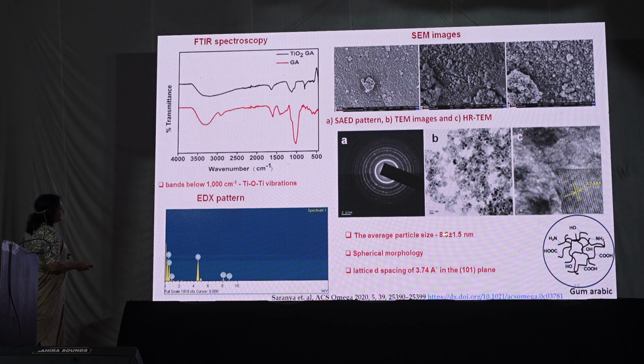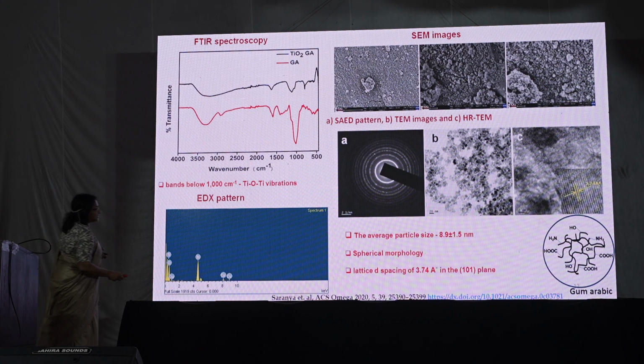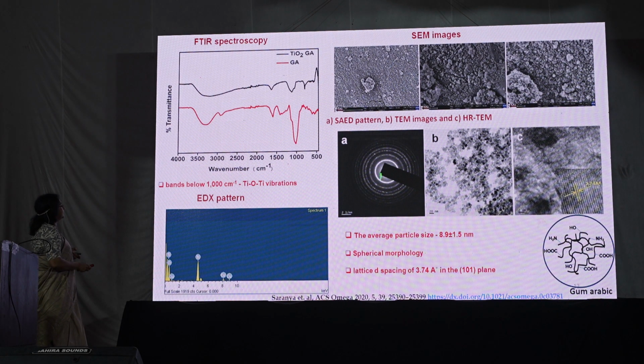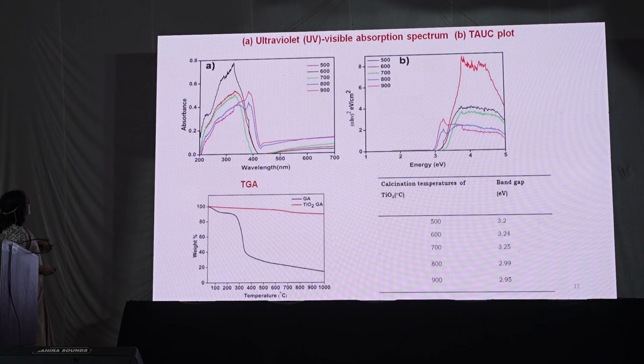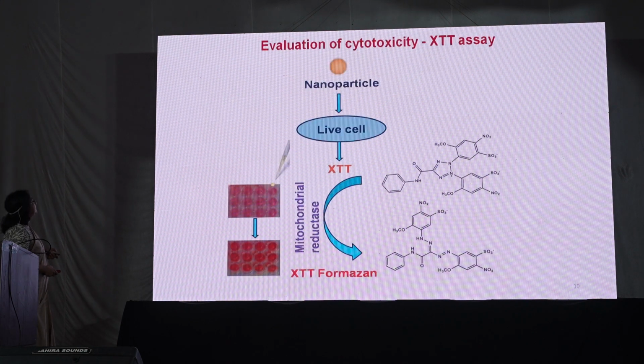And we got the nanoparticles with an average size of 8.9 ± 1.5 nanometers, and further these are characterized by SEM, TEM and EDAX spectra, and we can see the crystalline structure. From the IR spectra it is clear that the titanium-oxygen-titanium vibrations show the indication of the formation of these nanoparticles. And this is the structure of gum arabic. This is a biopolymer consisting of hydroxyl, carboxyl and other groups that can act as reducing and stabilizing agents for the formation of these nanoparticles. And these are the TGA and UV-visible characterization.